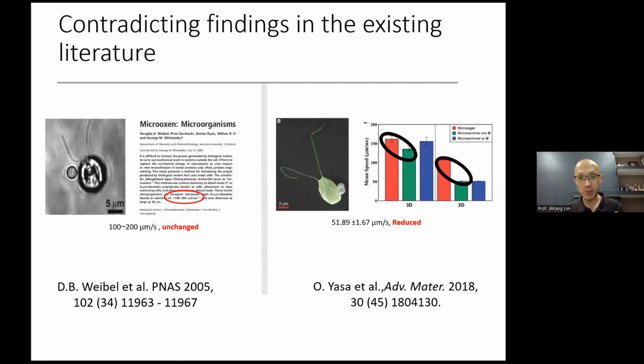And they publish in top journals using the same cell line as us, Chlamydomonas reinhardtii, using almost similar size of microbeads, magnetic beads. And what happened is this. Certain groups report there's no change of the velocity. The change remains 100, and some is even increasing. They could observe the velocity, actually the speed actually increased. And some report the speed, like us, actually been reduced.